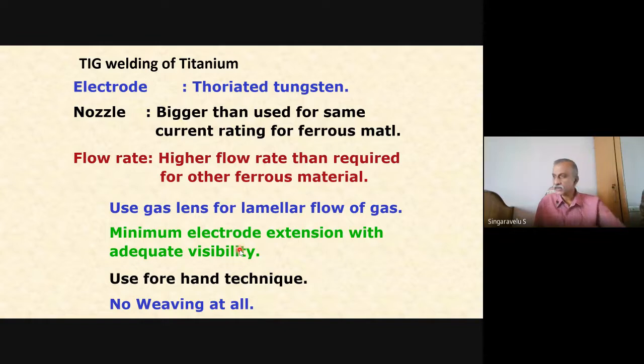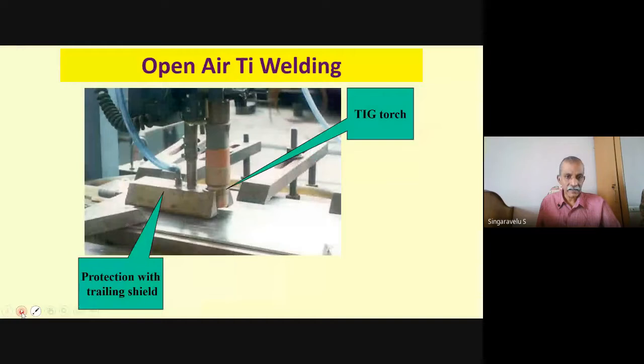Minimum electrode extension. Normally, you will know that the electrode tip will be protruding outside in the case of TIG welding. So its length should be kept to the barest minimum, or otherwise there will be a chance of touching this electrode to the titanium, which then gets contaminated. So the minimum extension is required. Use the forehand technique, no weaving at all, right? This is open air welding with manual